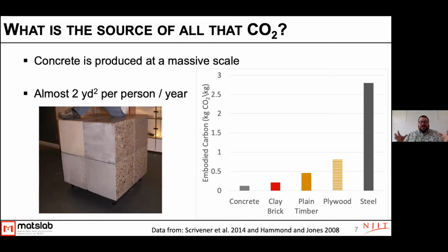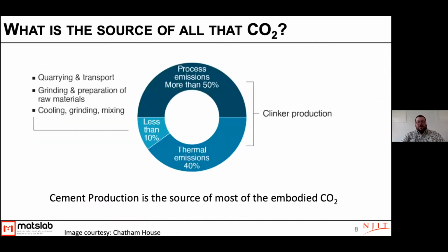And so you can start to imagine how much concrete we're making every year. On a per unit volume basis, concrete is one of the more low carbon emitting materials out there. If you compare concrete to steel on a per unit volume basis, it's much lower. But of course, we make so much more concrete than we do steel that its impact worldwide is much more prevalent. So that is a problem that we need to address to make sure that we can control that carbon.